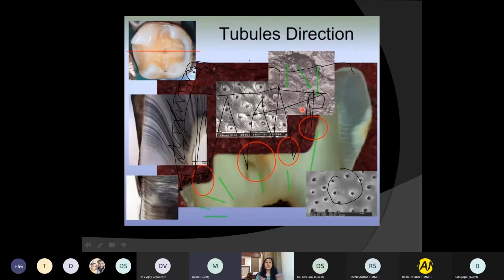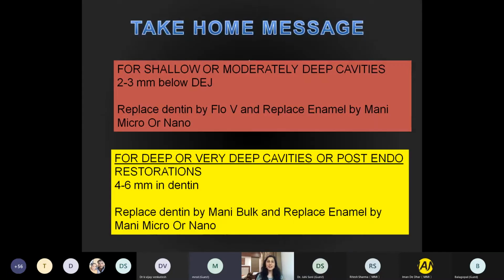So this is, in a nutshell, the take-home message. For shallow or moderately deep cavities, 2 to 3 millimeters below the DEJ, replace dentine by Flow-V and replace enamel by Mani Micro or Nano. But for deep or very deep cavities or post-endo restorations, which are 4 to 6 millimeters in dentine or maybe more, replace dentine by Mani Bulk and replace enamel by Mani Micro or Nano. So how simple it is.